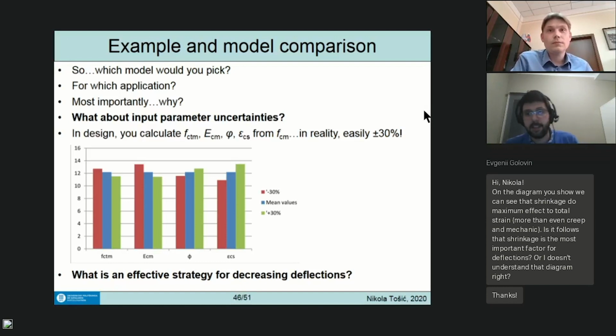In design, you would just have your concrete class and calculate tensile strength, modulus, creep coefficient, shrinkage strain. But in reality these can easily be plus minus 30%. As I showed here for creep and shrinkage, taking these values calculated by model code, you will never get at the same time a high shrinkage and low creep coefficient. In reality, they can differ.